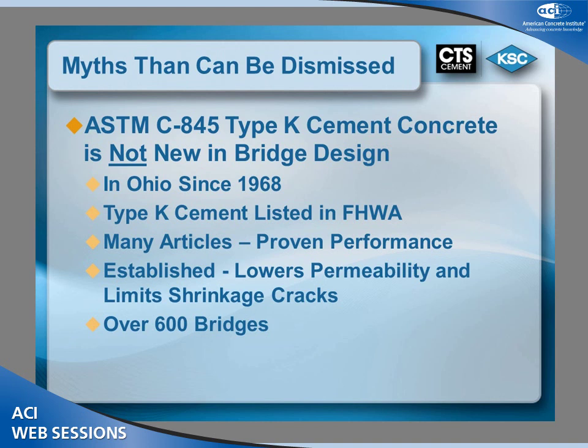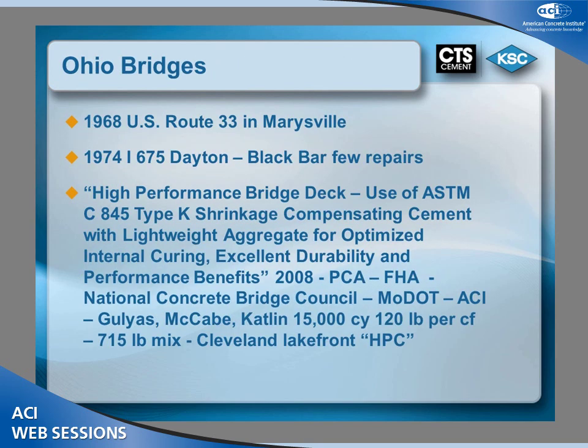Again, this ASTM C845 type K shrinkage compensating cement in Ohio has been used since 1968. There's been a number of articles written out there, numerous articles, found some that were written back as early as 1991, in Concrete International, Concrete Construction. We have established the fact that this concrete does have a lower permeability than traditional Portland cement concrete. And it has been used in well over 600 bridges. And again, we've lost count. Basically in Ohio in 1968, the first project there was US Route 33 in Marysville.